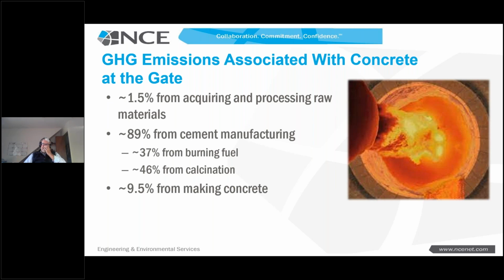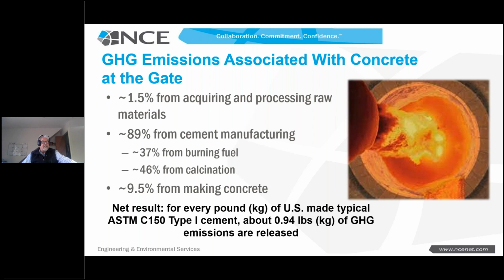Once we make the cement, that's over 90% of the total, just in the Portland cement. Only 9.5% of all of the rest of the CO2 associated with that cubic yard of concrete at the gate is from making the concrete itself. Net result is for about every pound or kilogram of cement made in the US, about 0.94 pounds of greenhouse gases are liberated, almost all CO2.